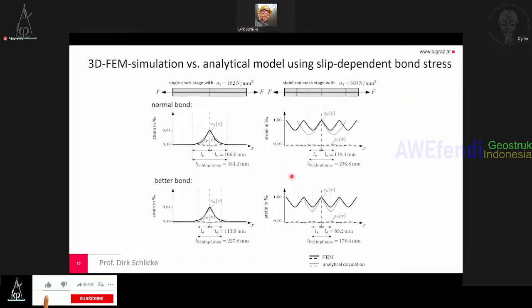We must check. If we compare now our analytical solution, this is in gray, with the FEM simulation, which is black, we see there's a very good agreement between these results for single crack stage, almost independent of what bond condition we choose. But if we go for stabilized crack stage, we see, okay, our simulation was rather a small diameter, so we must calculate with better bond. We have also an acceptable agreement. So for me, honestly, this was a surprisingly good agreement.